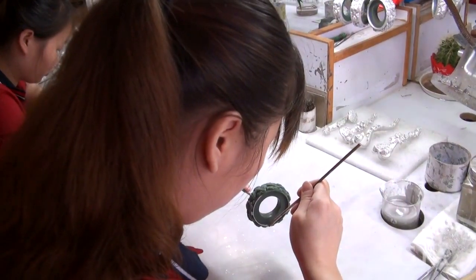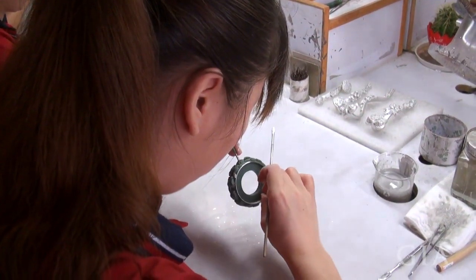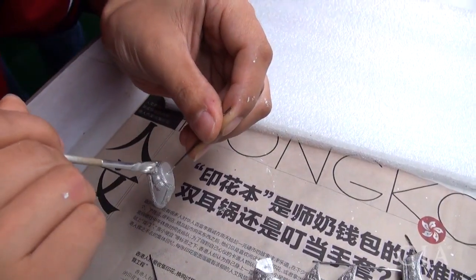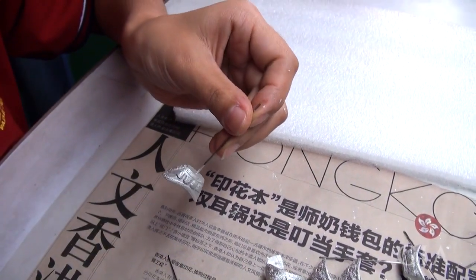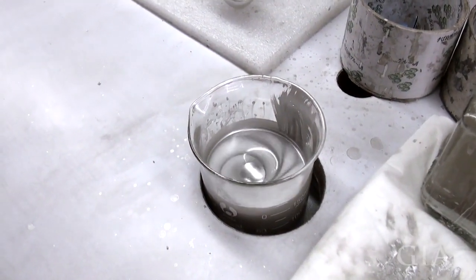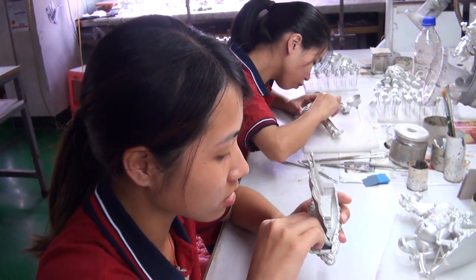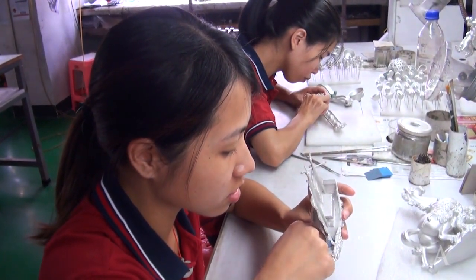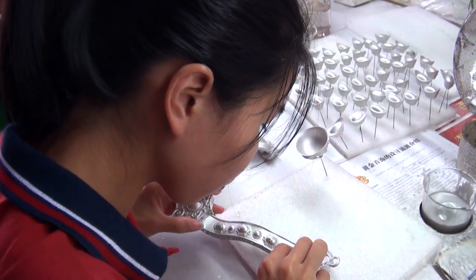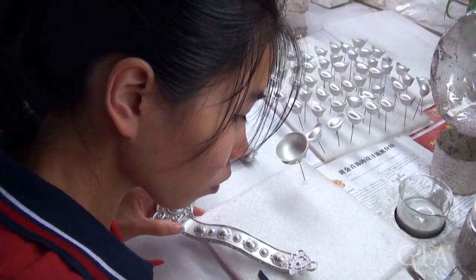The paint is applied by hand using a fine paint brush. This allows the jeweler more control in applying an even coat on the piece and in between all the fine details. The silver paint is constantly swirling to keep the content properly mixed. Workers examine the piece for consistency, and fine sandpaper is used to remove any imperfections that would show up in the final electroformed gold piece.